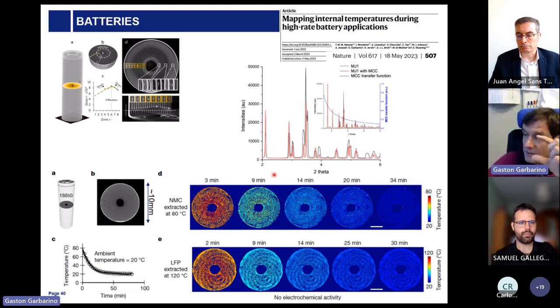The only thing is that as your material is very large in terms of penetration of the beam, you will see here in black the broad peaks, meaning that the quality of the diffraction pattern will be degraded due to the dimension of your sample, and you cannot do any interpretation or refinement anymore, because now you are summing up all over the sample. Okay, so the fact that we use this multi-channel collimator allows us to really probe a particular position of the battery and do in operando studies and measure the temperature inside the battery without touching the battery itself.